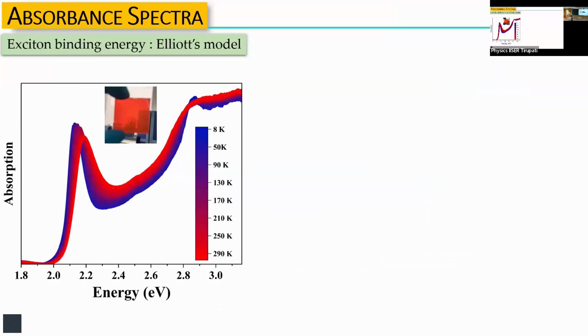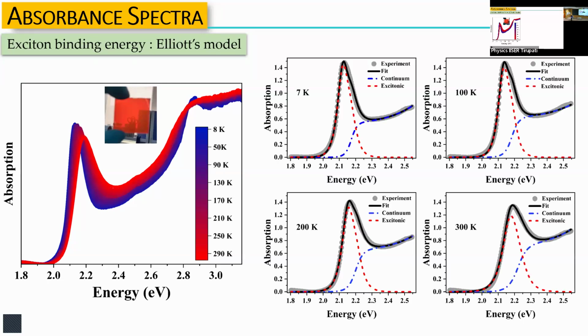But I'll point out the binding energy that I talked about. For that, she has to make a thin film sample and measure the absorption curve at various temperatures. Absorption curves tell you how the absorption changes with photon energy. The band gap is more than that. At this energy, it begins to absorb. This is the exciton forming signal, and this is the free electron-hole forming signal. So that is deconvolved, or decomposed, into an absorption coming from electron-hole, as electron-hole absorption, and the excitonic absorption. The difference between these two energetically is a measure for the exciton binding energy.